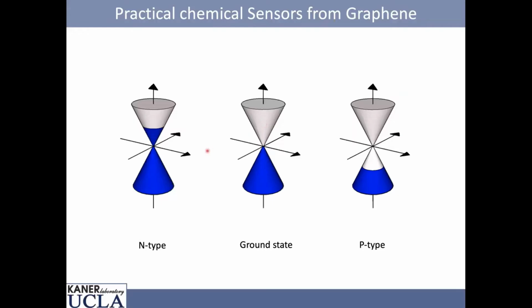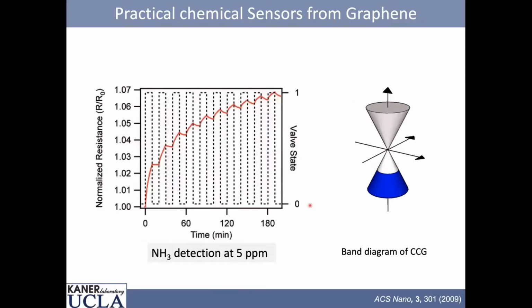Now, if you dope it N-type, what you're doing is you're adding electron density to the pi star orbitals. And so that should increase the conductivity. Conversely, if you p-dope it, you remove electron density from the valence band. However, that should add holes to the valence band and should increase the conductivity. So in fact, perfect graphene cannot be used as a sensor. But we're not actually making perfect graphene. We're making graphene with a little bit of oxygen because we make it from graphite oxide.